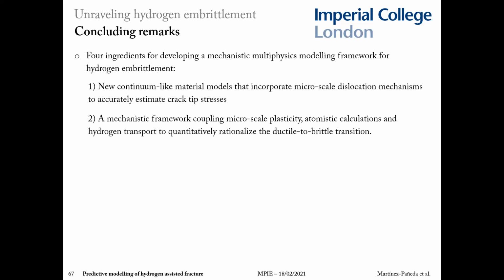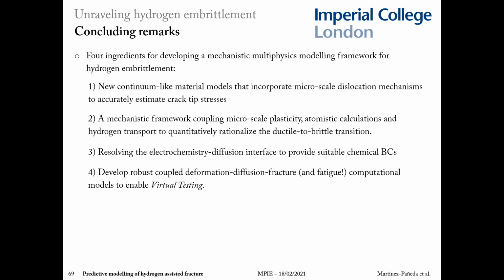Secondly, a mechanistic line of thought to rationalize the ductile to brittle transition is needed. And we came up with one by coupling microplasticity with atomistic calculations and well-established laws of hydrogen transport and equilibrium. And thirdly, by appropriately estimating the hydrogen content, so using rigorous models for hydrogen transport and interface reactions. And the fourth ingredient is developing compelling multiphysics computational tools that will allow you to deliver predictions that can be benchmarked against experiments and inspections, for which we use the phase field fracture method.